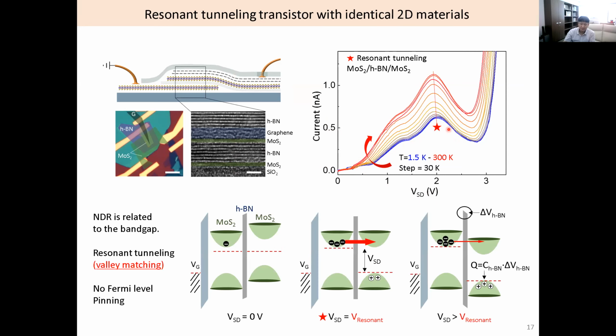So what happens? I'm claiming that this is a band gap of MoS2, and this is the situation. Because I made two MoS2 in valley matching condition, this is called valleytronics. You have heard about valleytronics with 2D materials. This is one valley for the conduction band of MoS2, and this is one valley for the valence band of this MoS2. Of course, they are not symmetric, so we have a little bit different initial doping state. And as I said, we have very weak gap state. It's not like silicon. In silicon, we have strongly pinned N-type and P-type states, depending on the dopant. But here we can change the Fermi level. So this is called an ambipolar transistor. Both electrons and holes can be used for transport. So this is the initial condition.